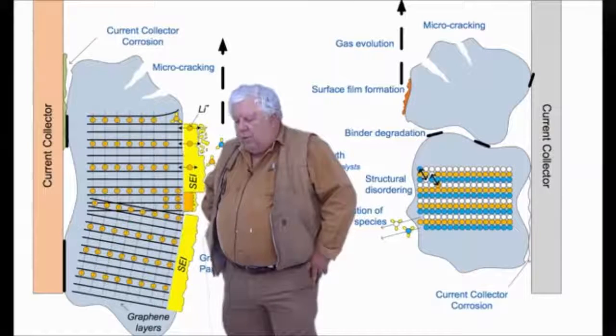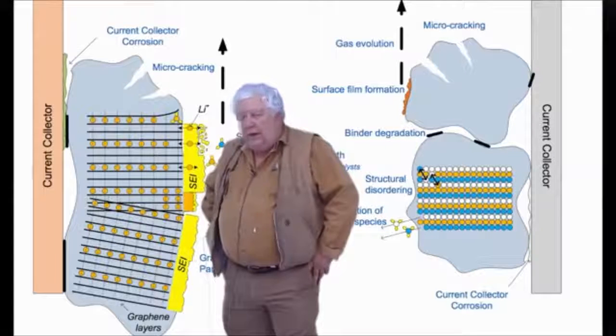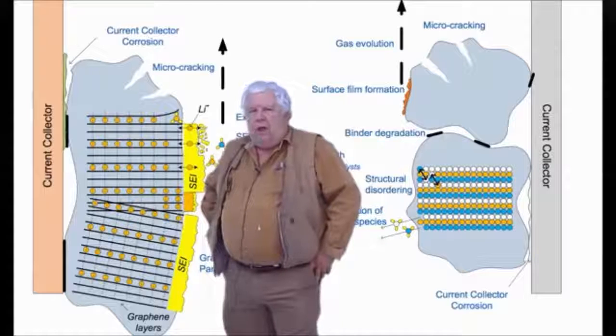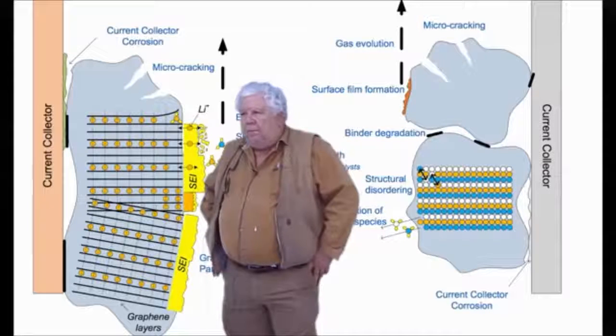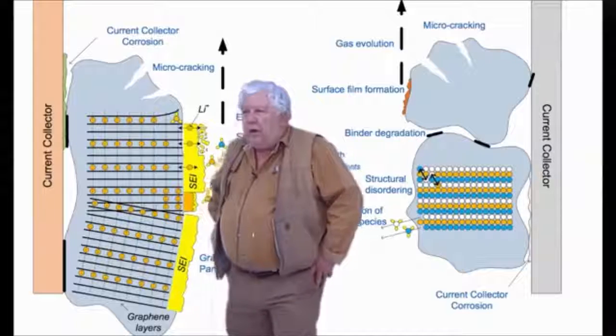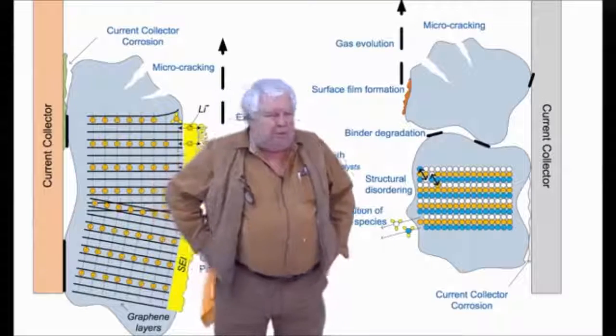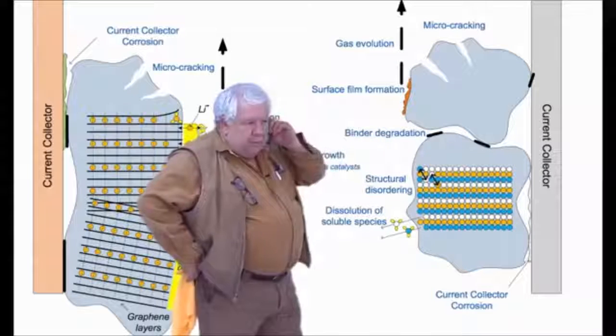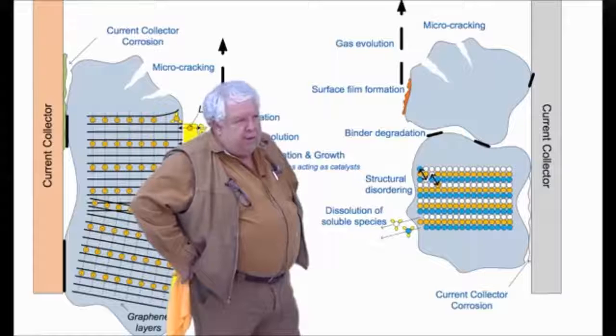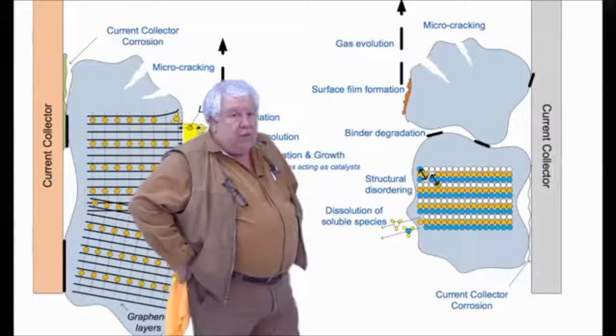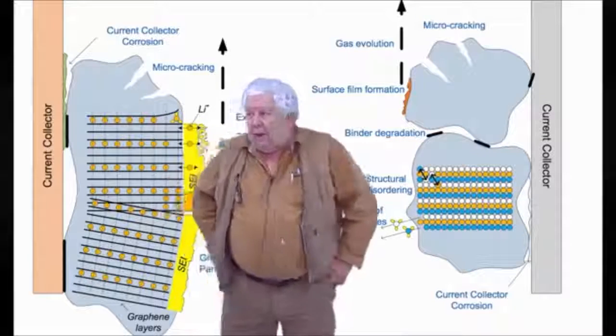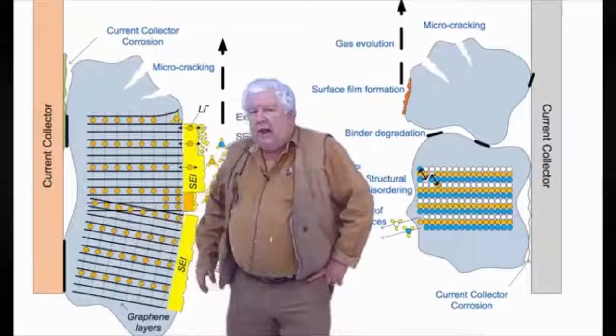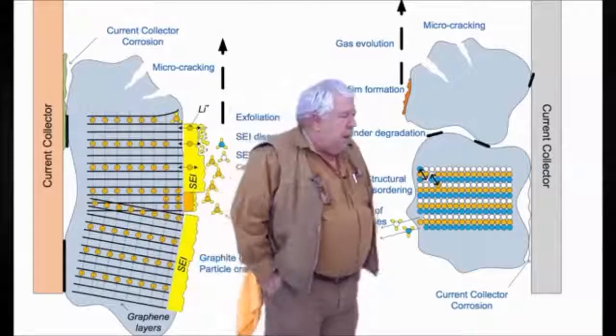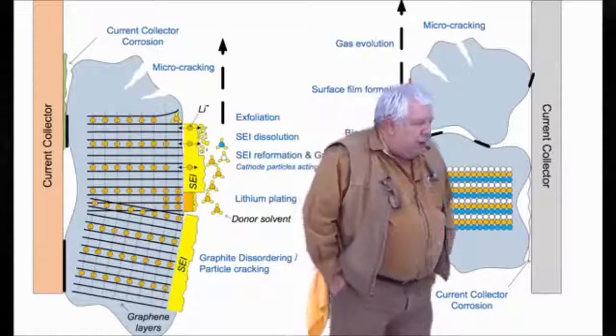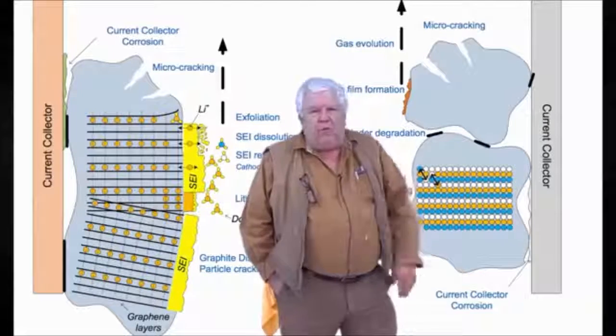And so the real problem is the gradual and then accelerating breakdown of the solid electrolyte interphase layer, which, in reacting with the lithium ions, gives off an increasing level of heat and goes into a thermal runaway situation. If that catches up the cathode, it's kind of all bets are off. You will not get it to stop burning until it runs out of oxygen. And halon and so forth on top of it doesn't have any effect because it's getting the oxygen from the material itself. So I hope that shows you what happens when you overcharge the cell.